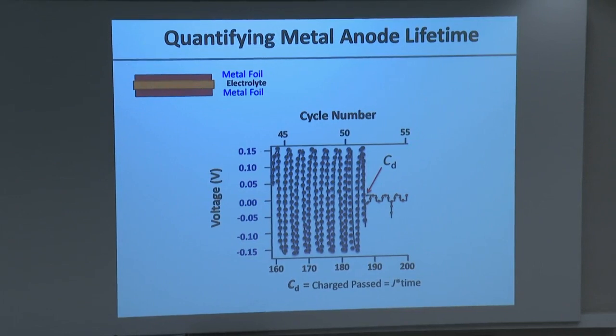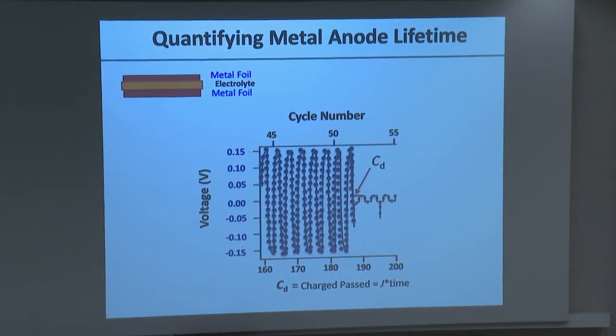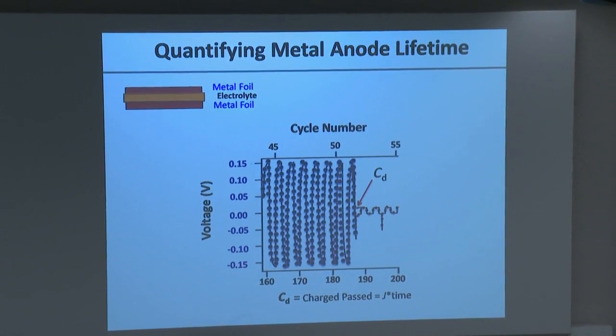So to cut a long story short, we use two different methods to evaluate efficacy. One method is called the galvanostatic plate strip experiment. So we apply a constant current and take lithium, or any metal for that matter, from one object, in this case a foil, oxidize it to the ions and deposit on the second element, again a metal foil. And we do it at constant current, so we take lithium from one place, strip it, plate it on the next one. Once we do that for a certain period of time, we reverse it, and we basically measure the voltage. If this system was behaving in a simple Ohm's law-like way, we would get a response like this, okay?